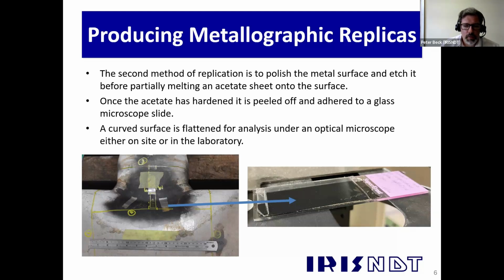At this point, the acetate sheet will gradually harden as the acetone dries off. You can see on this pipe that we've sprayed it black, and that the replica is also black. The reason for spraying it black is to give us a contrast when we look at it under the optical microscope.